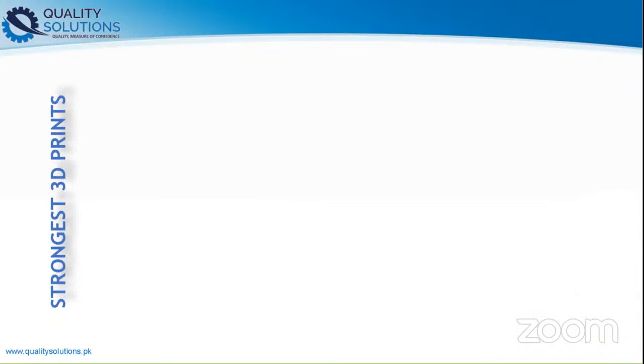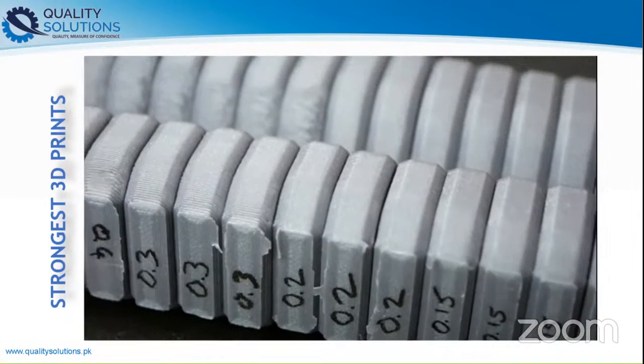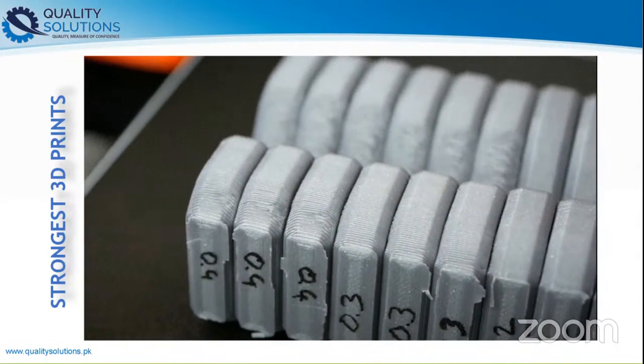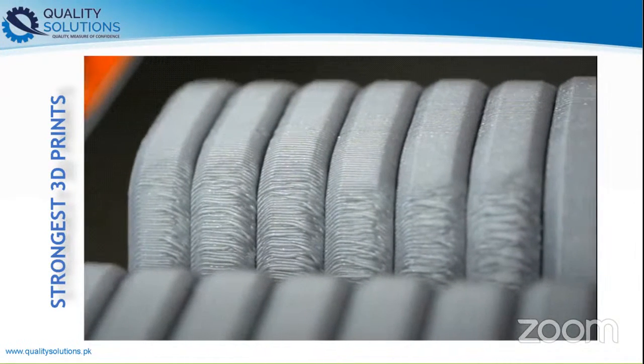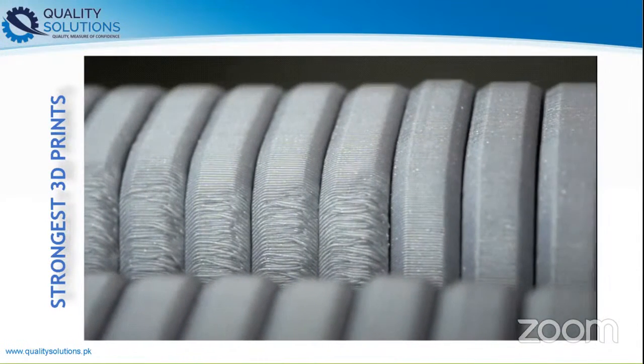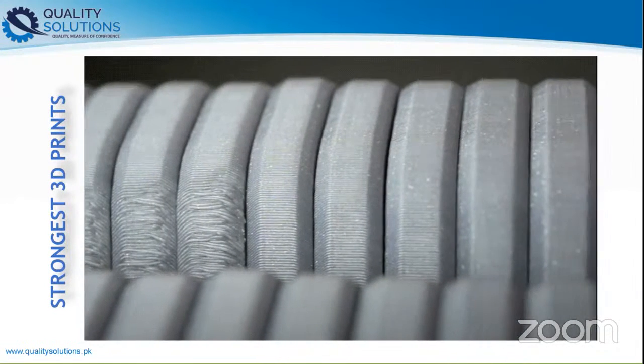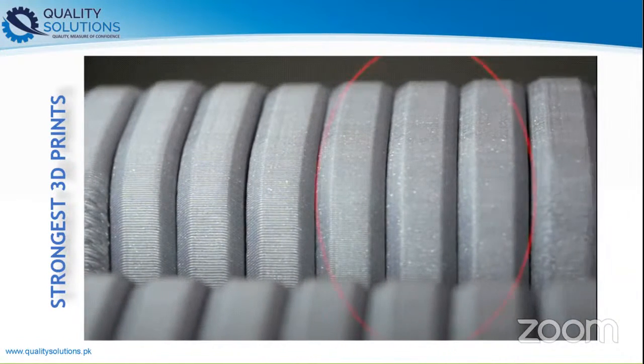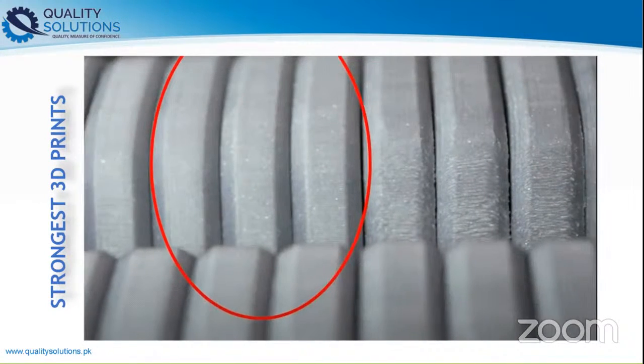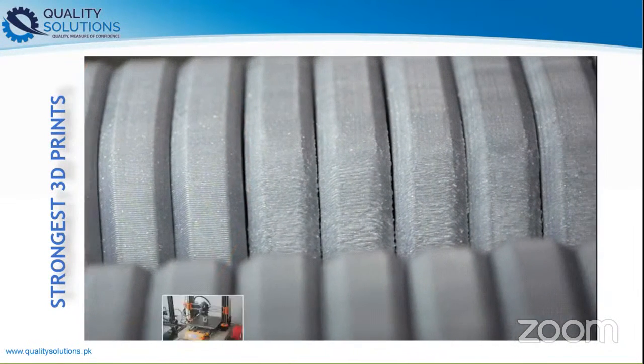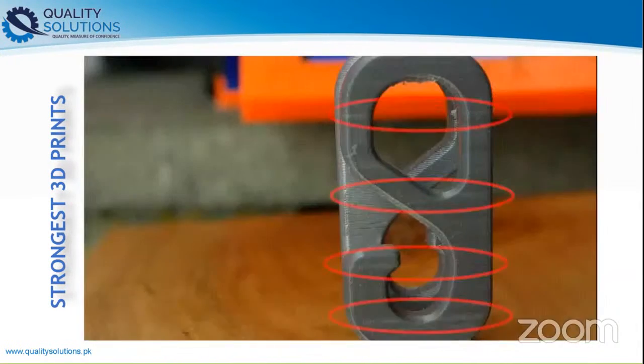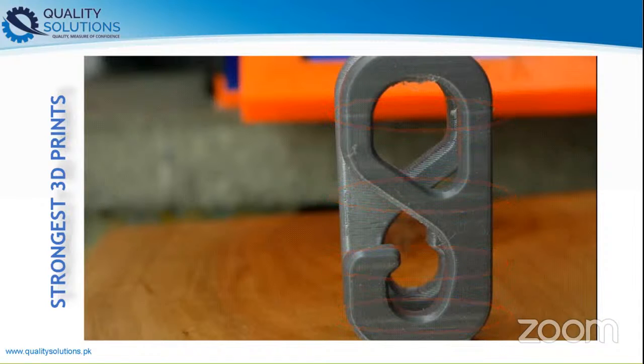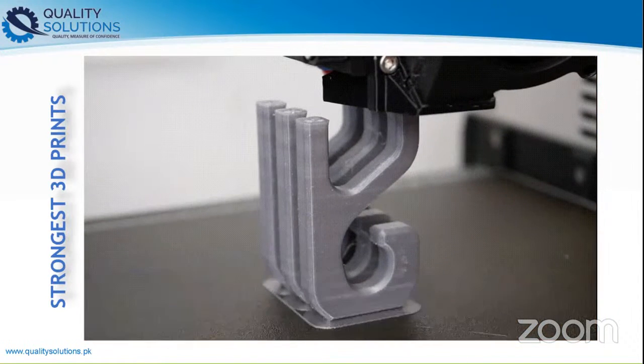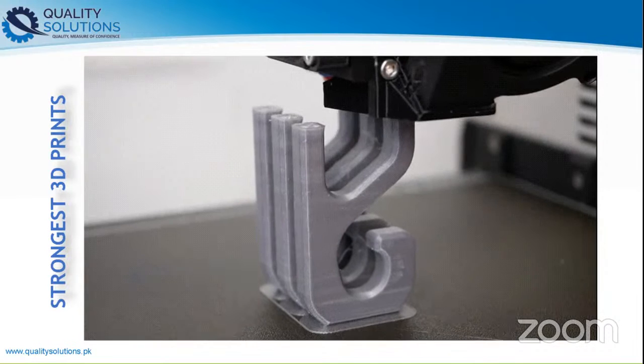Another result that was interesting for us is the print quality, which in my opinion didn't improve much. As you can see on the screen, the thinner the layers got, the side surfaces usually look better, but all in all, the sweet spot in our opinion was 0.15 mm. Another thing we noticed is that the color of the part started to get irregular, especially at 0.05 mm. This is probably because the material is in a molten state for the longest amount of time, messing with the pigment and maybe even the base polymer.